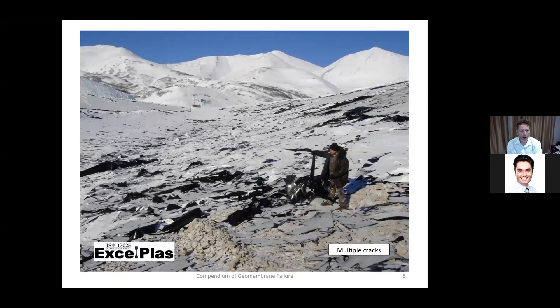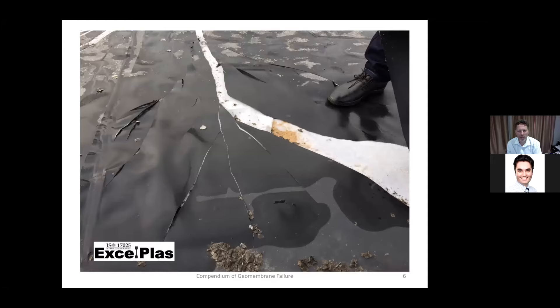With high crystallinity and low strain capability comes stress cracking — environmental stress cracking. All polyethylenes, particularly HDPE, are susceptible to stress cracking; it's just a question of timeline. HDPE also has a low multi-axial tensile elongation of only about 15%, so it doesn't cope well with differential settlement. As a consequence it cannot be prefabricated — it has to be field welded because it can't be folded without damage. In very cold climates below minus 35°C, HDPE can shatter via rapid crack propagation due to its high crystallinity.